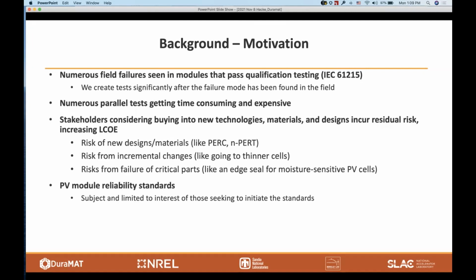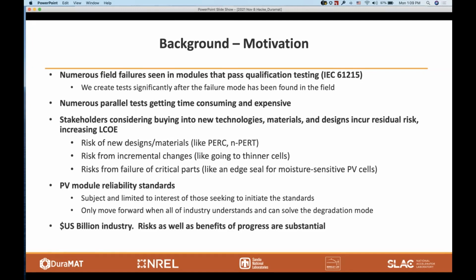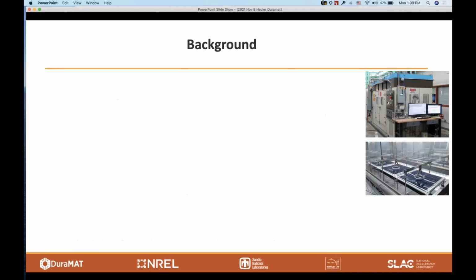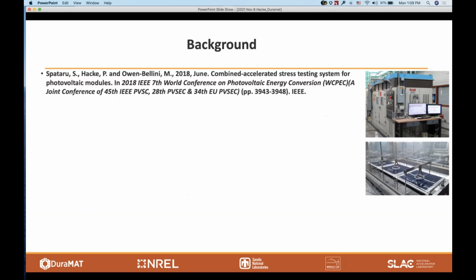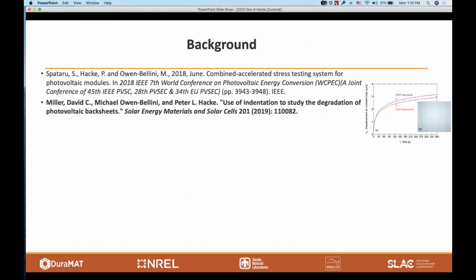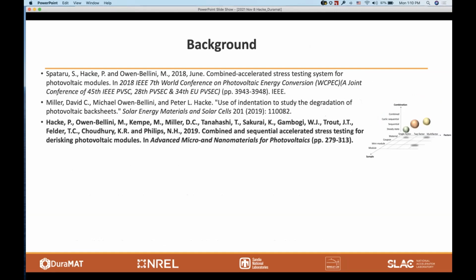PV module reliability standards are subject and limited to the interest of those seeking to initiate the standards, and they only move forward when all of industry understands and can solve the problem. So we see room for improvement here, and that's why combined accelerated stress testing is introduced. In our previous literature, we've discussed the equipment in a 2018 IEEE paper. We've discussed how indentation hardness can be used to show how cracking in PVDF is associated with embrittlement. Again, indentation hardness showed that. It's been reproduced by a number of other techniques.